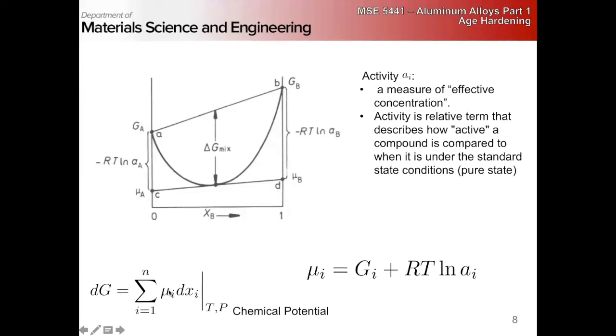If we look at our definition, right? So it's the change in Gibbs free energy by changing the composition a tiny way is equal to the chemical potential of element A in the phase times the differential in composition, right? So essentially what it tells us is we can find the tangent line to the Gibbs free energy curve and extrapolate out to pure A and pure B. And that gives us the chemical potential of species A in the mixture and the chemical potential of species B in the mixture.